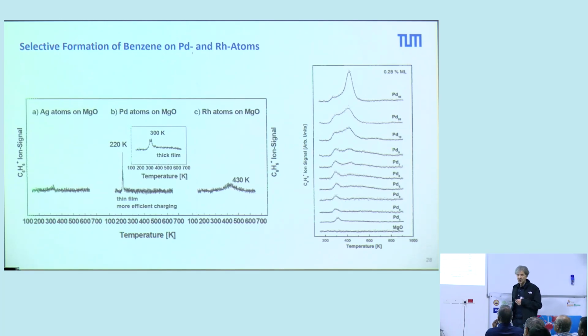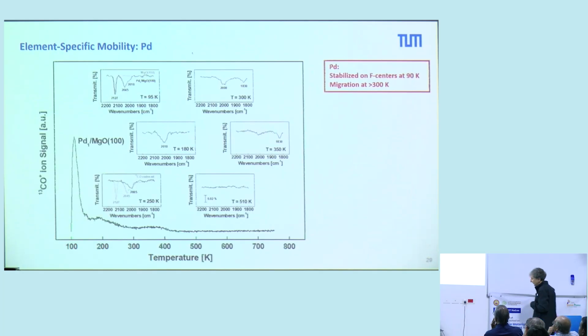Now the question is, are these indeed single atoms? Because we go up to a given temperature. Therefore, we studied with simple experiments IR. We used a probe molecule CO, and we're looking at the vibrational frequency as a function of temperature. And on palladium atoms, you see a typical on-top vibrational frequency of CO at low temperature. Then you can heat up the sample. You change a little bit the shape, you have a different coupling of the CO molecules, which gives the shape, but you have still a characteristic for an on-top bound CO molecule.